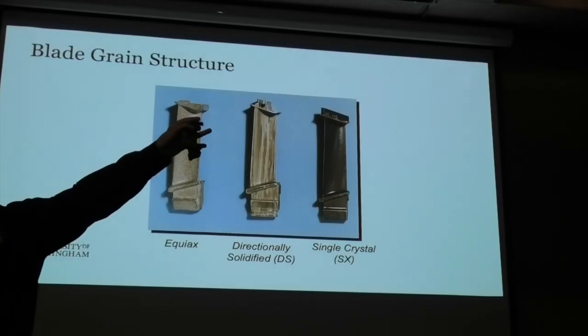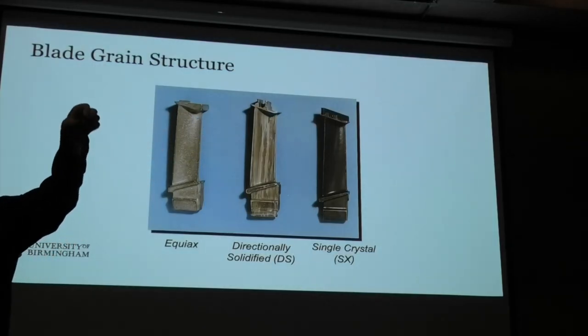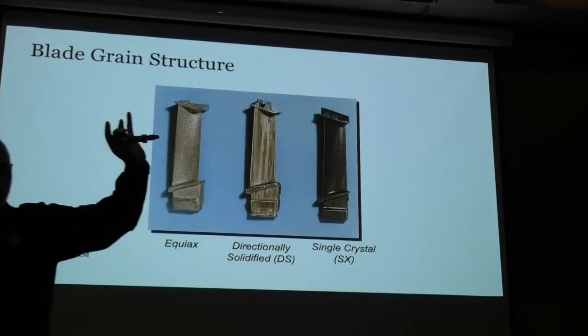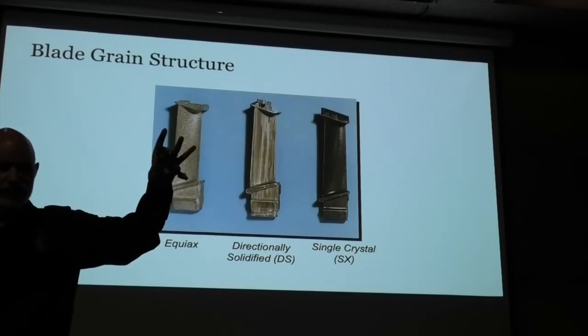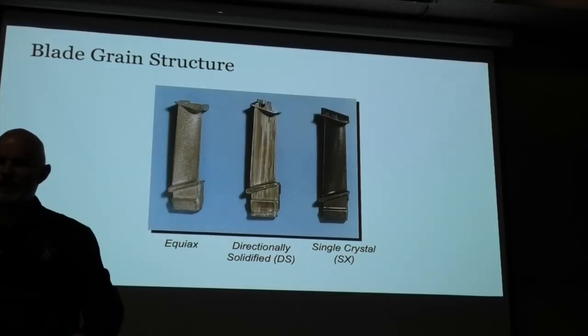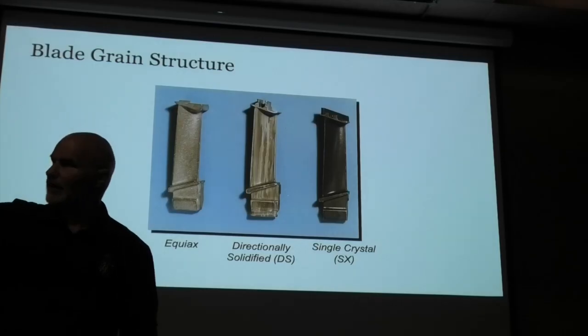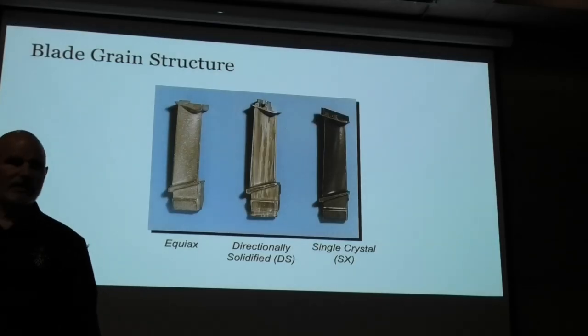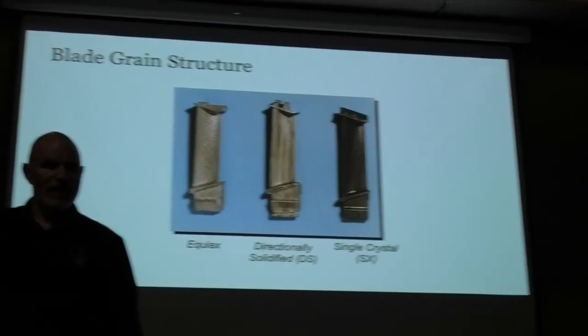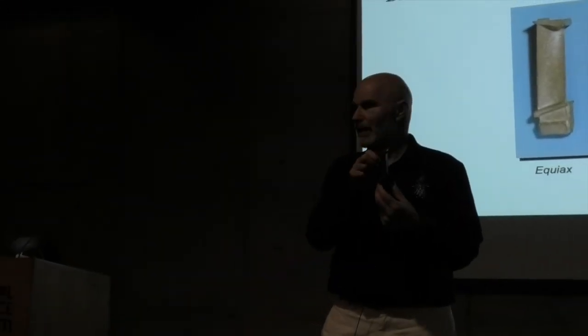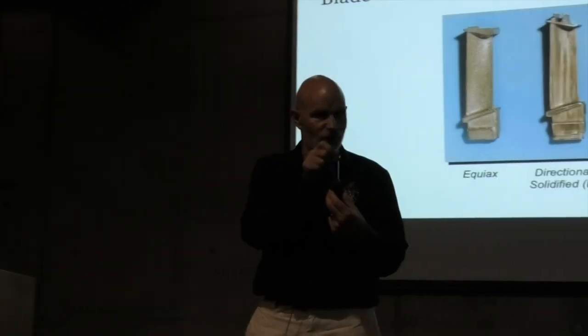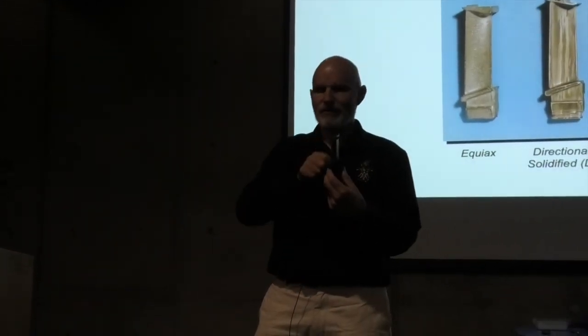If you look at it, it's etched up. You'll see there's some fairly fine grains in there if you look closely. I've chemically etched the surface so you can see the grains. This is a directionally solidified part we developed in the 1970s, 80s, where we decided we'd have really long grains in the direction of maximum stress, so the grain boundaries weren't being pulled apart. Instead of your sugar cube being pulled apart, we'd have long, thin grains, and you pull along the length of them. That made it much stronger. So we went for directional solidification.